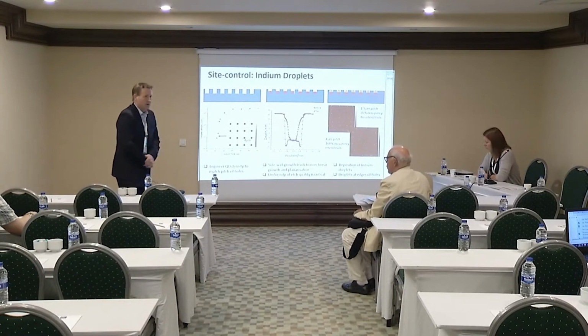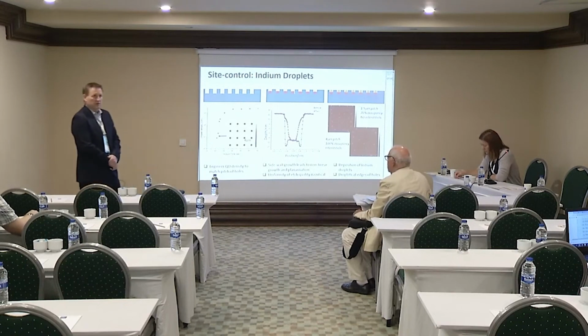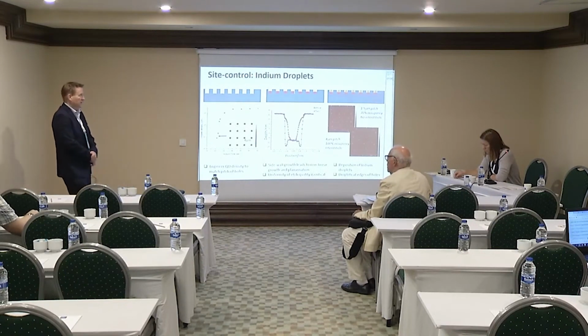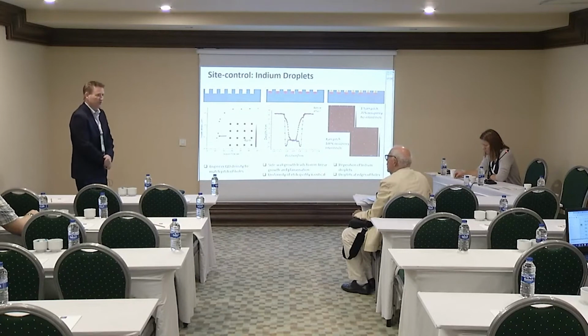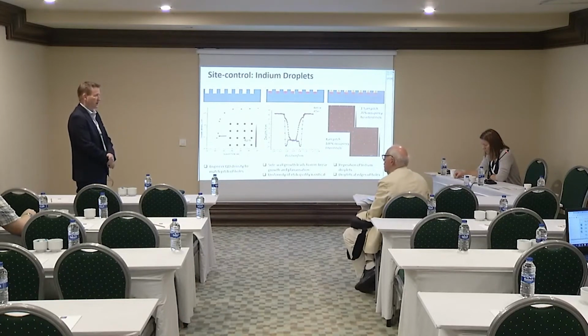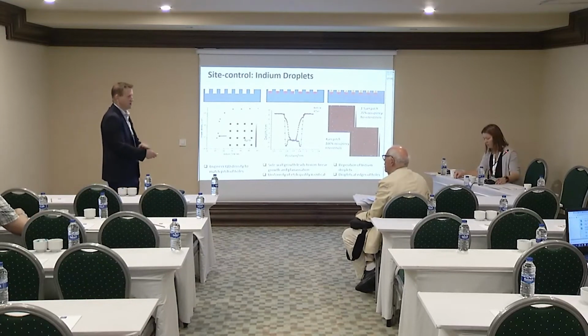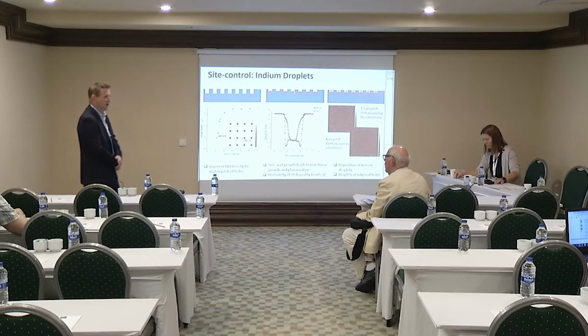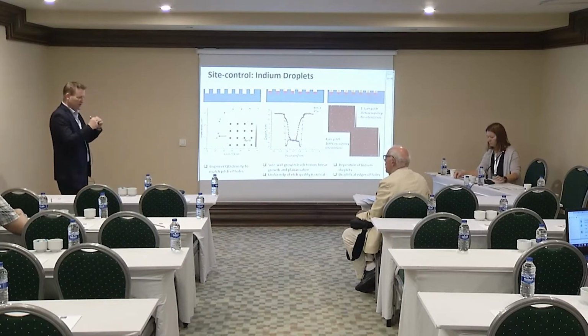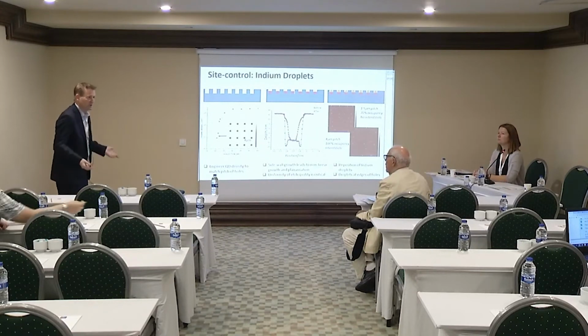Less than 1 micron, yes. We've gone down to, I think, of the order of 500 nanometers, around 300 nanometers. There isn't significant interaction between the holes in the E-beam process. As you get very dense, you just need to be slightly careful of proximity effects in the E-beam, but the etching process itself is fine.